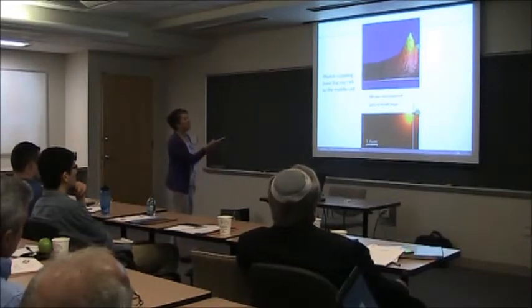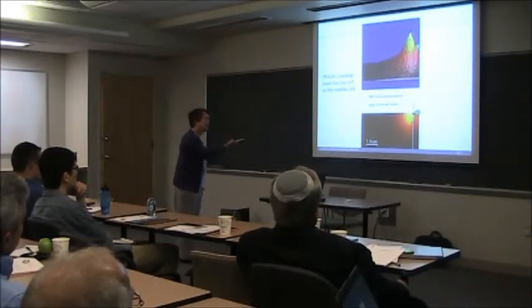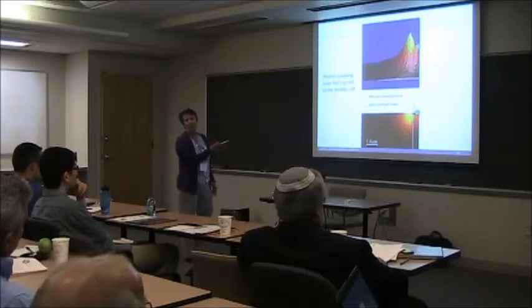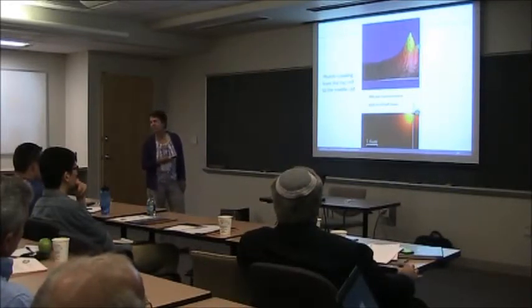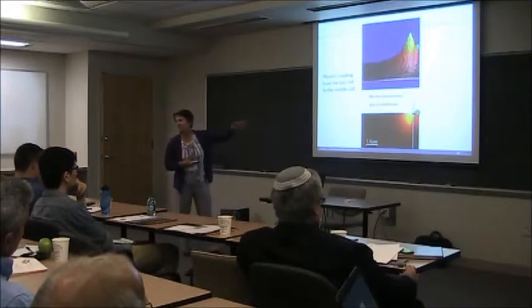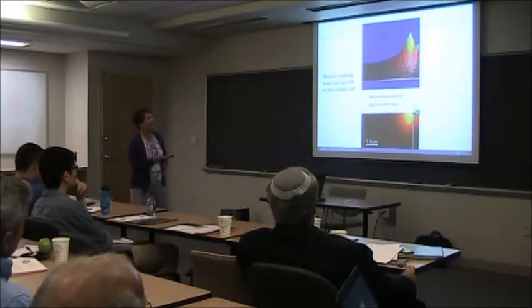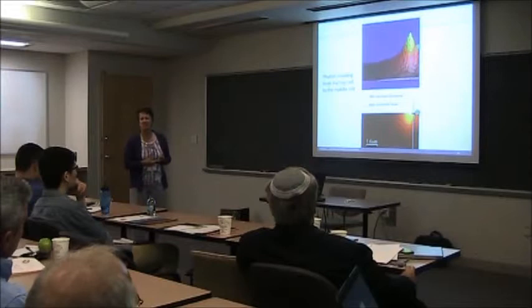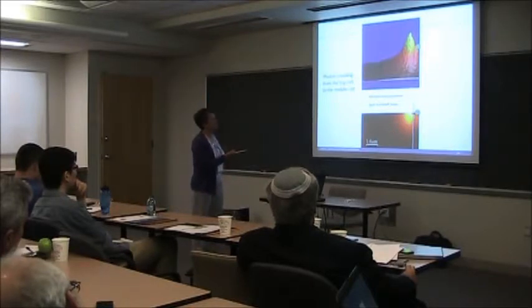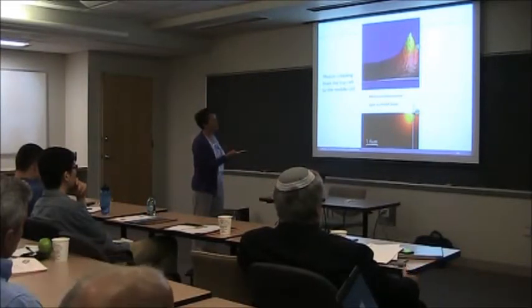This is light generated in the gallium indium phosphide, which is red, and then the fraction of it that goes this way gets reabsorbed, right, by the lower band gap material, re-emitted, and produces 880 nanometer light. So this is what is called photon coupling or photon recycling in the solar cell world. And the state of the art of this stuff now is such that they are actually figuring out how to minimize and recapture this kind of emission at high efficiency. Because again, even a few tenths of a point in this business is important. So we can actually look in literally now and see it, see the beam here. So imagine the photon here, a stream of photons here, and then light being emitted in the neighboring stuff.